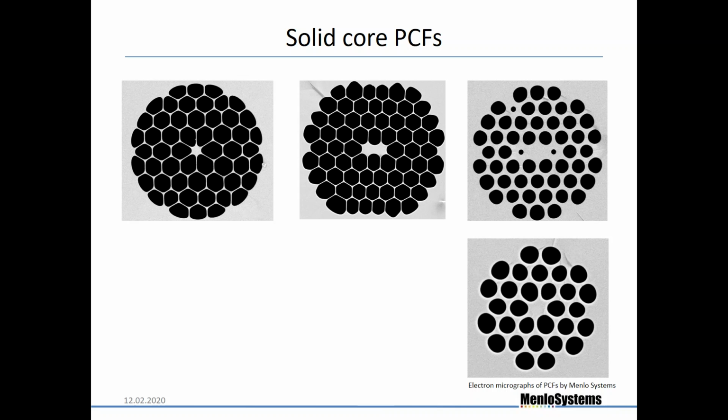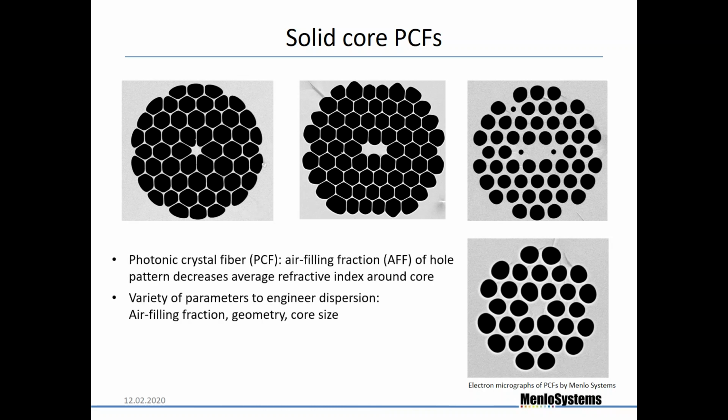And the air filling fraction in the hole pattern gives us control over the index step. And this gives us a very strong handle on the index step, and it allows us to add a lot of waveguide dispersion to the material dispersion, and it also allows us to have very strong mode confinement here. And this helps to enhance nonlinear effects, to enhance the nonlinear coefficient.